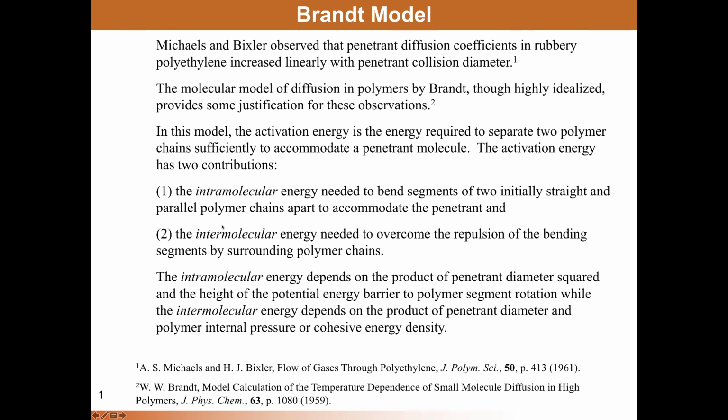Brandt also argued that if you moved apart two polymer segments, or moved apart polymer segments around a penetrant to create a volume through which the penetrant could diffuse, those polymer segments were pressing against their neighbors around them, and there was an intermolecular contribution.